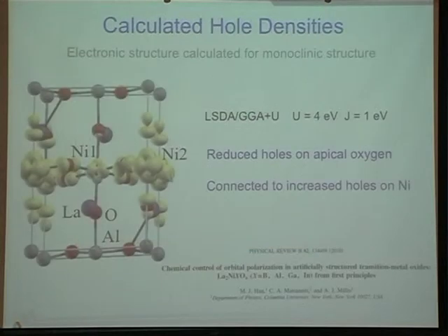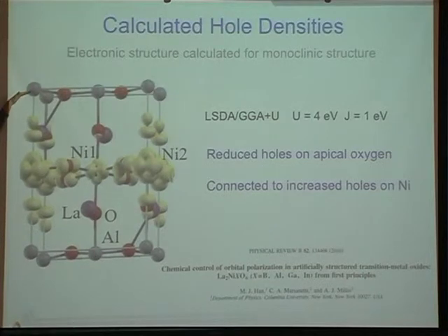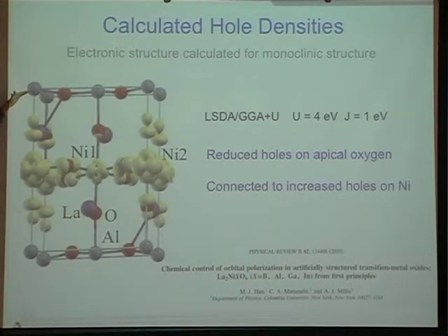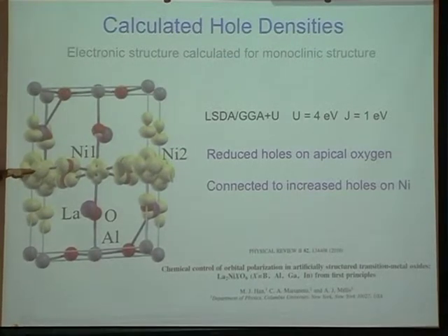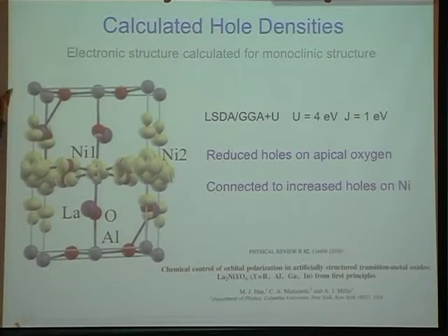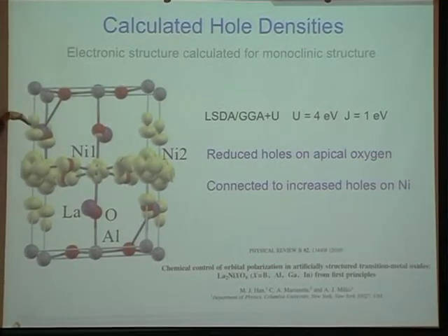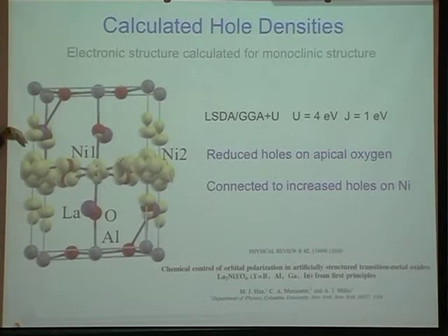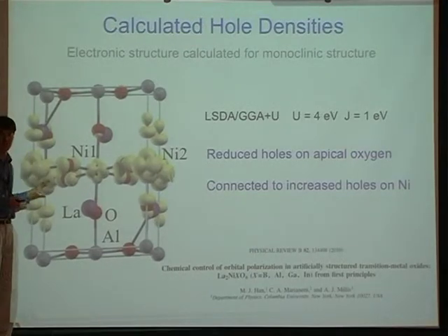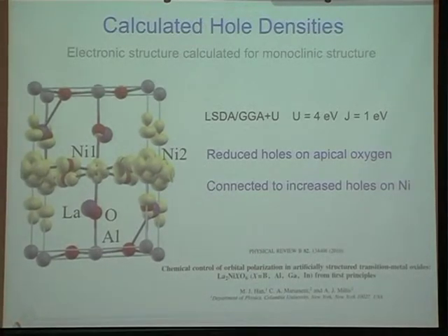So then what happens at the interface is a very interesting, at some level, simple chemistry problem. On the one side, I have aluminum. Aluminum is formally ionic. It wants oxygen to be 2-. Over here, I have nickel. Nickel wants holes on oxygen. There's a battle across the interface. And what happens is the aluminum actually pushes some holes off of the apical oxygen and back into the nickel manifold. And so in the end, you generate an orbital polarization through basically interface chemistry. And Andy also wrote a paper about this at about the same time. So this is an interesting phenomenon where you're controlling orbital polarization through basically interface chemistry, not through stretching the bonds.